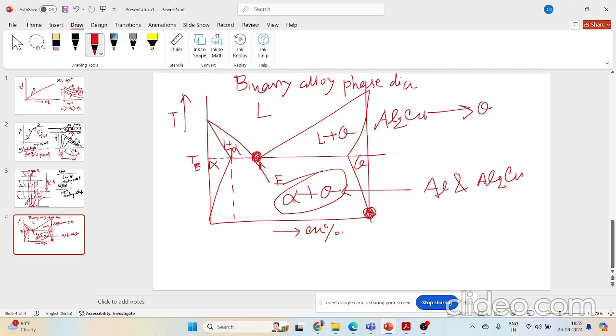So, what is the necessary criterion for precipitation hardening to happen? The solubility of copper in the alpha phase should increase with increasing temperature, right? Let's take the example of aluminium with 4% copper. What I will do initially is some solution heat treating, right? I will heat the alloy in the alpha phase temperature range until it becomes a solid solution.